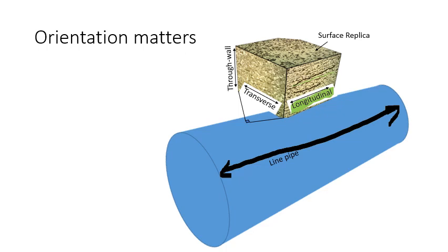Banding are these regions of dark phase that are aligned to the left and right, indicating that as the steel was deformed into plate or strip, the regions of pearlite were elongated, mostly in the longitudinal direction. Now, there can also be banding in the transverse direction, but it is not as common. So we could see banding this way as well, but it's not as common. Now, we'll almost never see banding on the surface.